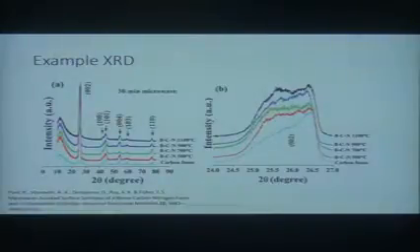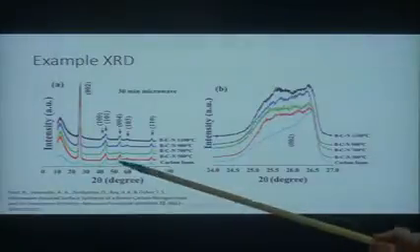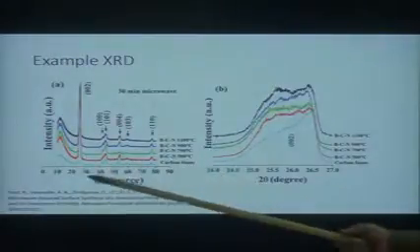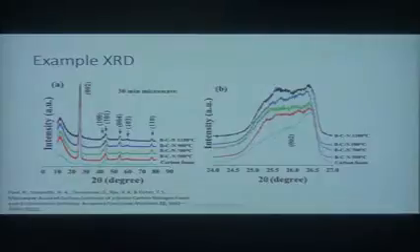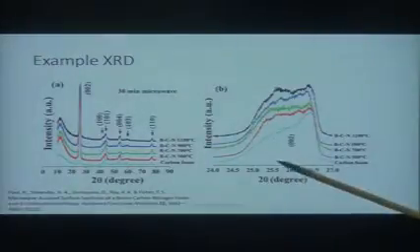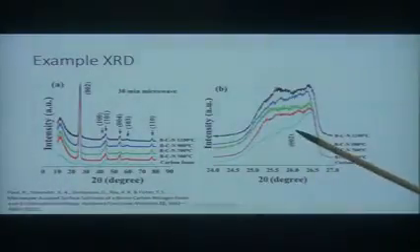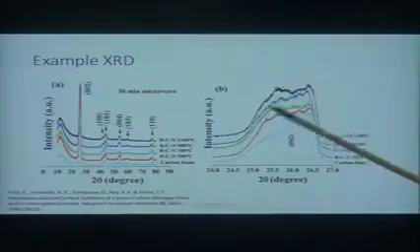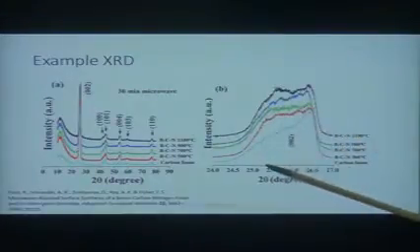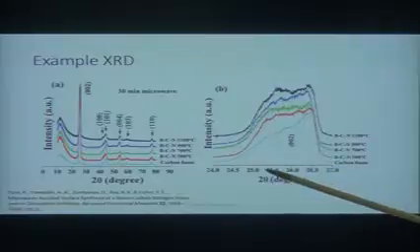But then what we've done is we've added boron and nitrogen to this material, and you can't really tell a big difference from the survey scan. That's the wide range of 2 theta angles. But when you look at the main peak, the 002 peak, you see that there's other content that starts to come in this area of about 25 to 25.5.